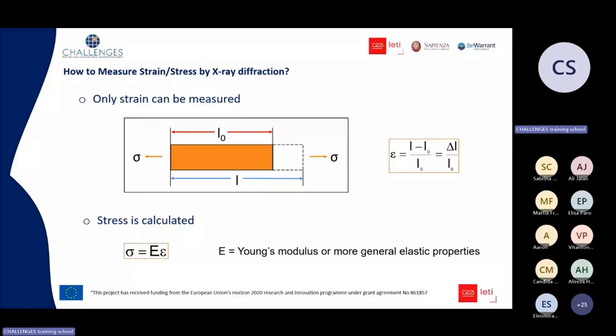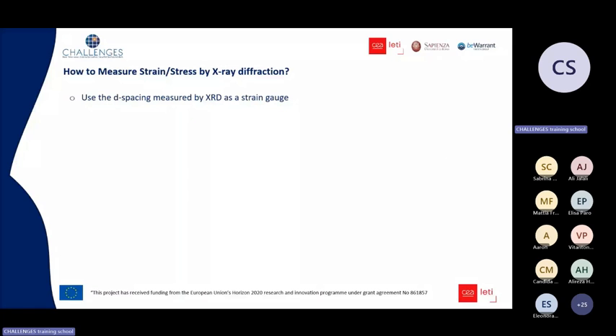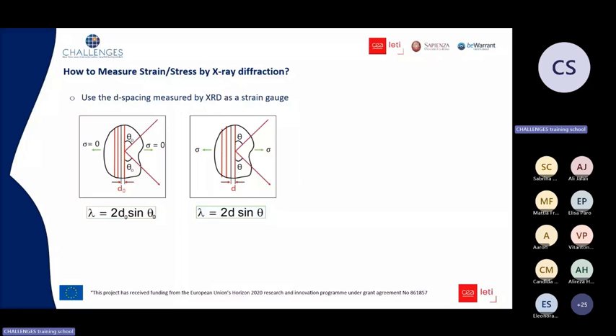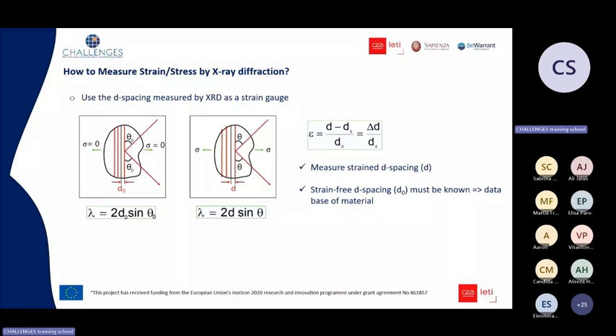So the idea for X-ray diffraction is to use the d-spacing measured by X-ray diffraction, through the Bragg law, as a strain gauge. For example, if you have a material without stress, you can measure a d0 spacing from a theta zero angle of diffraction. And if you apply a stress, the d-spacing will change, so you have a strain, and the Bragg angle of diffraction will change. So you can calculate the strain by calculating the d-spacing variation relative to the initial value of the spacing. If you know the strain-free d-spacing, d0, you can calculate the strain.